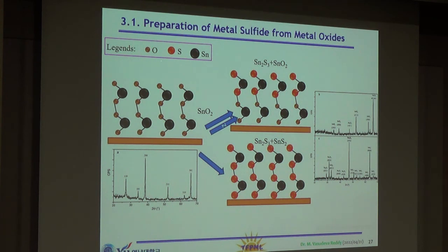First I would like to see the reaction mechanism of the sulfur with the tin oxide, so initially I am planning to study on the glass substrate. Once I understand the reaction mechanism, then I will plan to prepare on the molybdenum substrate. If I go directly, I may have more complications. Sometimes oxygen will diffuse into the molybdenum, so molybdenum oxide will form or some other issues will come. First, at least I should be familiar with the reaction mechanism of tin oxide and sulfur, then I will go on to the molybdenum substrate. Thank you.